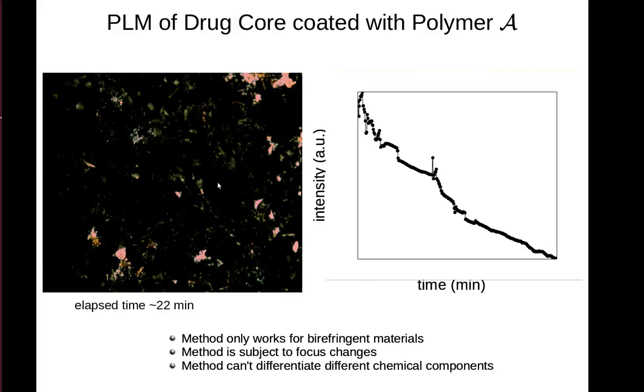Now, it is a very difficult measurement because as the polymer dissolves, it changes the refractive index in the focal plane, and the microscope has to be readjusted periodically for focus, and hence some of the periodic changes out of focus during the experiment. Another problem with the experiment is it only works for birefringent materials, which is fine for most APIs since they are optically active. However, it doesn't tell us anything about the excipients, such as the polymer or the binder in the core.